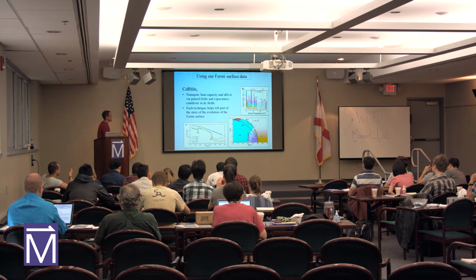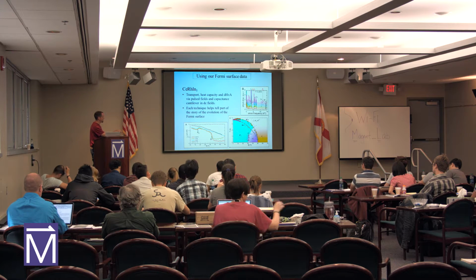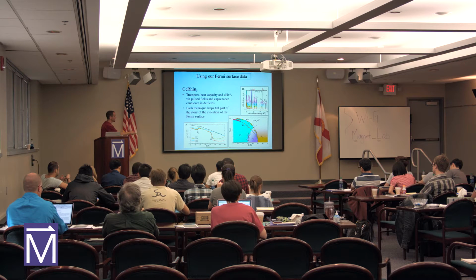The phase boundary was determined by heat capacity measurements and de Haas-van Alphen measurements out in Los Alamos. We did some Hall effect measurements here in Tallahassee, and we didn't see any quantum oscillations with the transport data, but the Hall effect did show us some kinks in the Hall signal, which tells us that something's happening to the carriers and helped us to further define these phase boundaries.